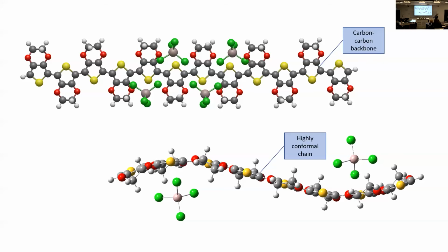Interestingly, the challenge when you're trying to model PEDOT, as opposed to, say, a more conventional battery electrode or crystalline material, is this highly conformal chain. This creates a complete configurational nightmare in trying to find energy minima, because these things can adapt and there are lots and lots of positions that they can end up in. Trying to find one on which to base your calculations is difficult, and much of the pre-work to this particular piece of research was working out just how much that matters, and what the dominant effects and the not so dominant effects are.